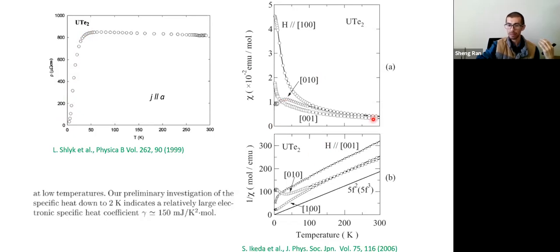And from magnetization, if you look at the B-axis, it's Curie-Weiss behavior at a high temperature. At about 50 K, the magnetization drops, again likely due to the Kondo coherence. And they measured the specific heat, the gamma, which is proportional to the effective mass. The gamma is about 150 millijoule per K squared mole.